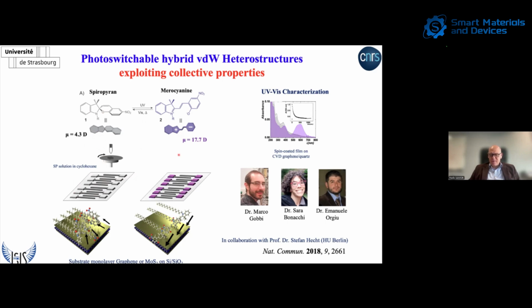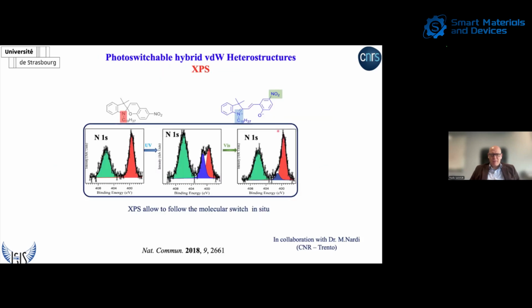Are we certain about that? Well, we are certain because we can do UV-vis absorption of a monolayer of our spiropyran supported on CVD graphene that is transferred on quartz. And we can map this with UV-vis absorption spectroscopy. We can map this also with X-ray photoelectron spectroscopy.